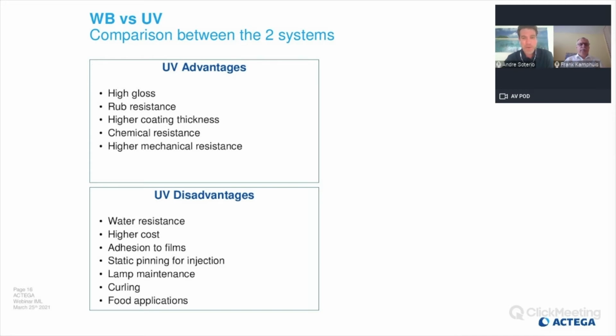This is also one of the defining points: static pinning at the injection. With UV, depending on the way you apply and depending on the usage, you might have some static pinning problems at the injection site. Then we have as well the lamp maintenance. Lamp maintenance is one of the most important things when using UV coatings. You have to change the lamps often, so that you have a good curing of the coating, and consequently good quality labels.